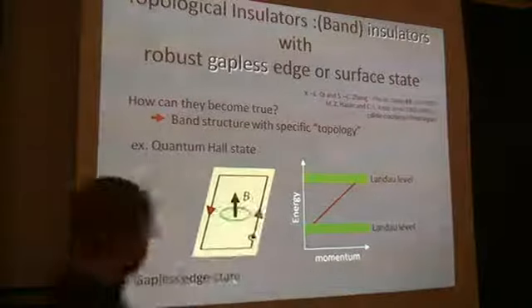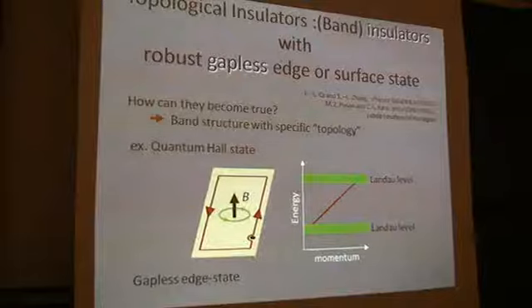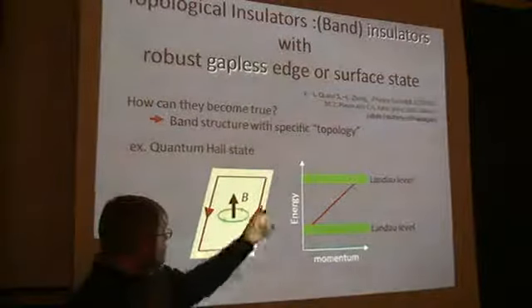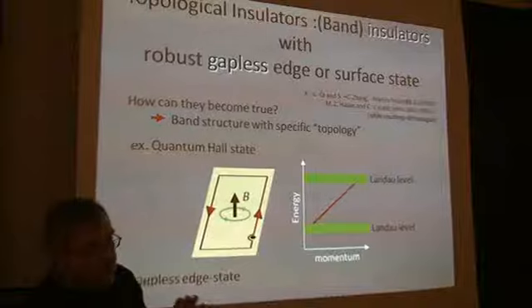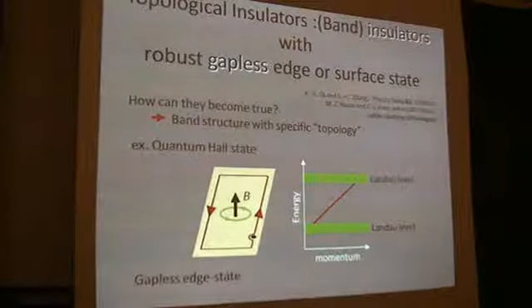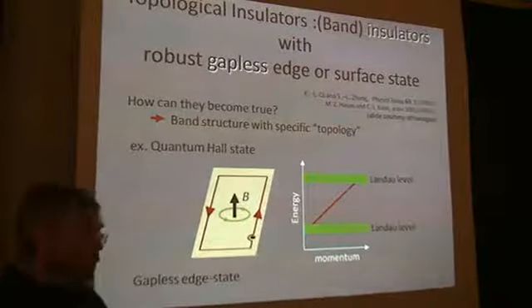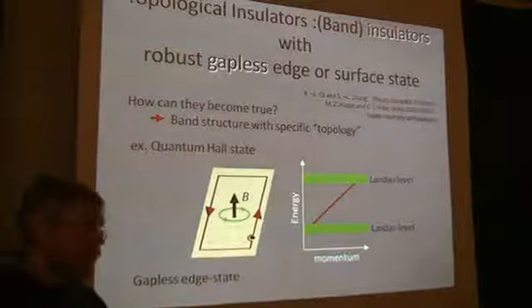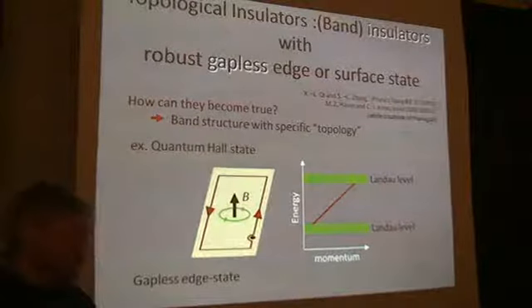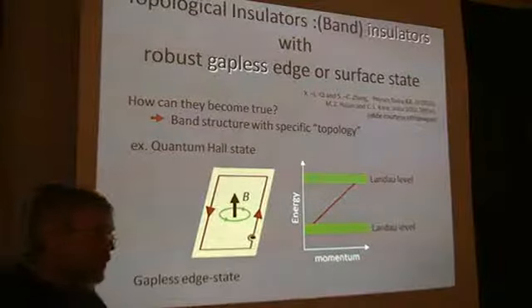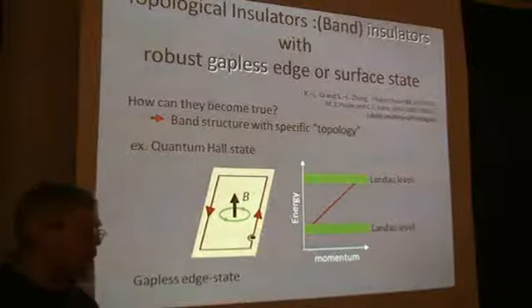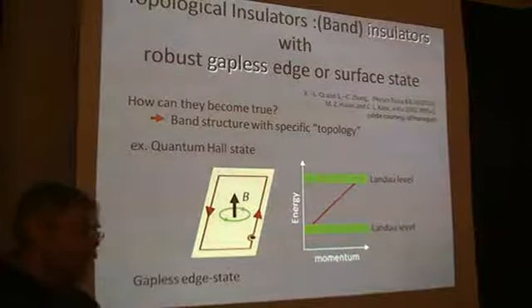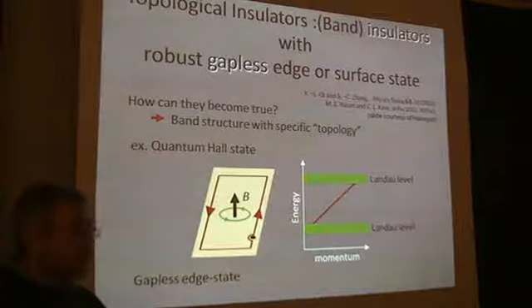And as Victor pointed out, if I have a defect, what happens in the case of defect scattering is that when the electron comes in, it just goes around and moves on. So the crucial piece of the protection of one-dimensional edges in the quantum Hall effect is that you suppress the backscattering. There is no backscattering at 180 degrees. Now for the two-dimensional scattering problem in the topological insulator, I'm going to argue that you don't have a suppression of 182 degrees or 179. So you punch out, in the scattering integral, a set of measure zero. The support of the exact zero is just zero.